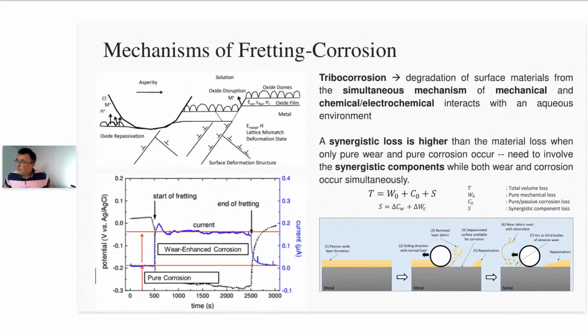My perspective with many of these devices is that it's inevitable that you're going to get breakdown or detachment of these oxide films on the surface, and the extent will very much depend on the nature of the environment that it's in, but also the tribological conditions. But what's particularly fascinating about these materials, and particularly when we're talking about passivity, is that once you've abraded that surface, the oxide film will spontaneously reform, principally because the underlying surface is incredibly reactive. The metal will react with any oxygen or water that's present at the interface, and then it will spontaneously reform these passive films.